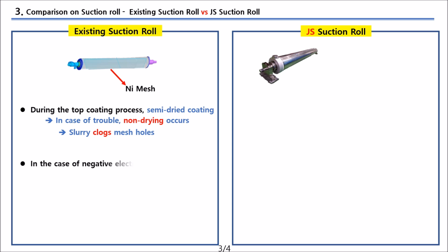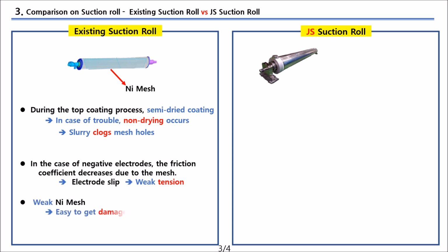In the case of the negative electrodes, the electrodes slip and their tensions get weakened because the friction coefficient decreases due to the mesh. The characteristic of the nickel mesh of being weak and easy to get damaged even by a small impact causes problems of an increase in costs for securing spares and such.